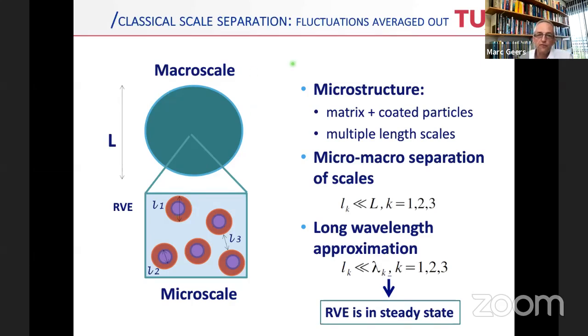So here is what happens if you do it in a classical way. In a classical way, we often talk about fluctuations that live at the microscale. In the classical method, you average those fluctuations out so that they don't contribute to the macroscale. For the dynamics we're considering here, it means that all the micro length scales are much smaller than the macroscopic length scales. For this particular problem, it also implies that the length scales at the microscale are much smaller than the wavelengths in the different phases of the material. Then the RVE is in a steady state and there cannot be any internal vibrations. This is what we call the long wavelength approximation.